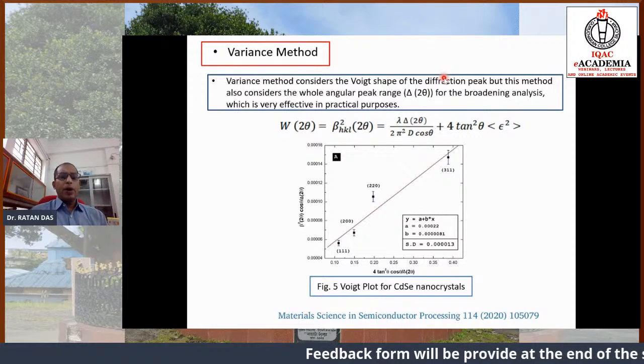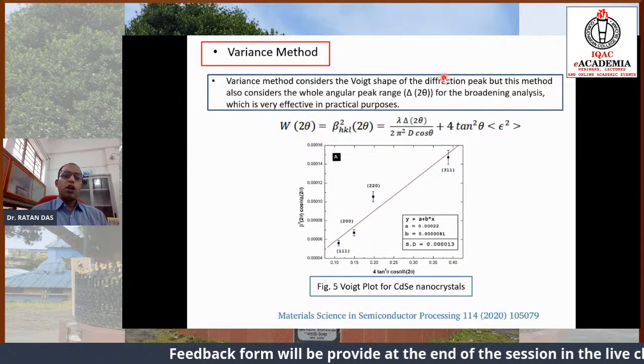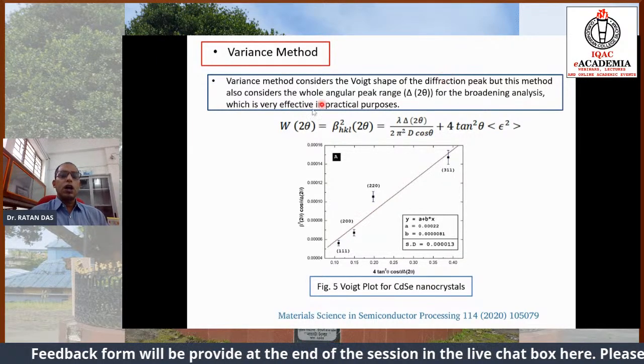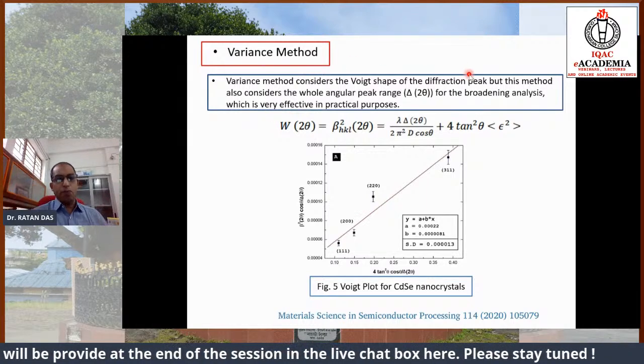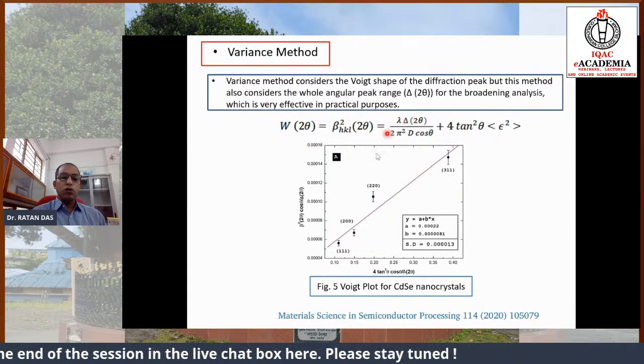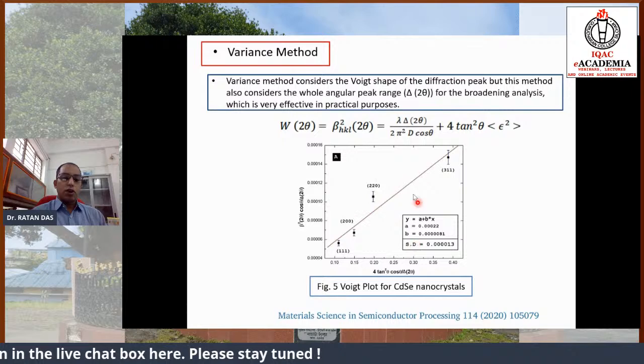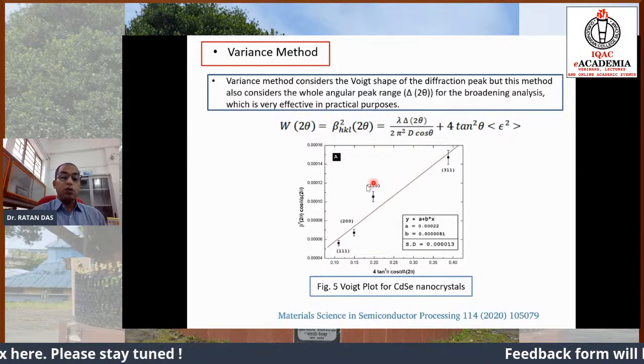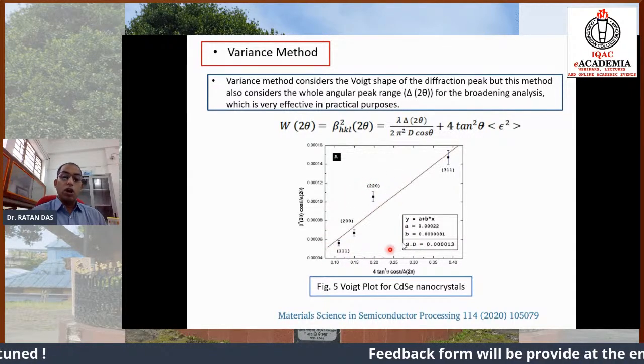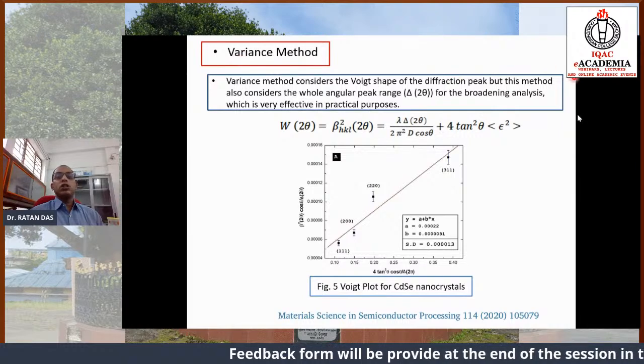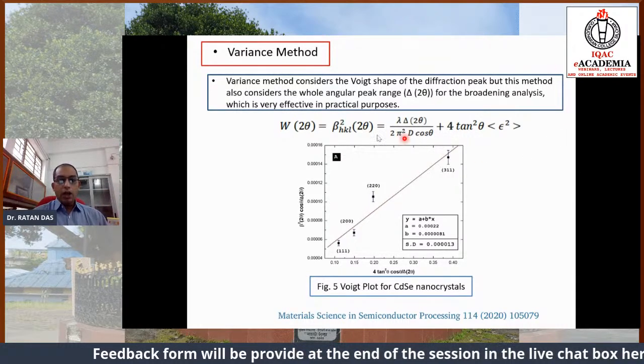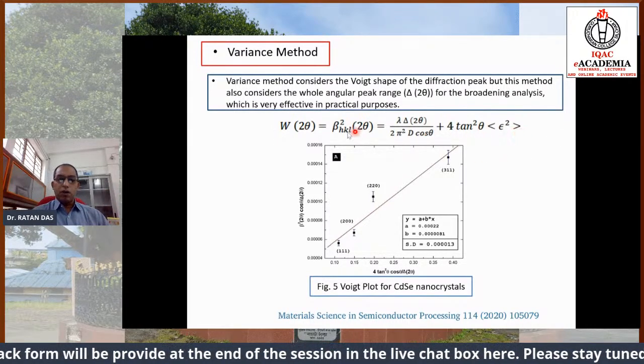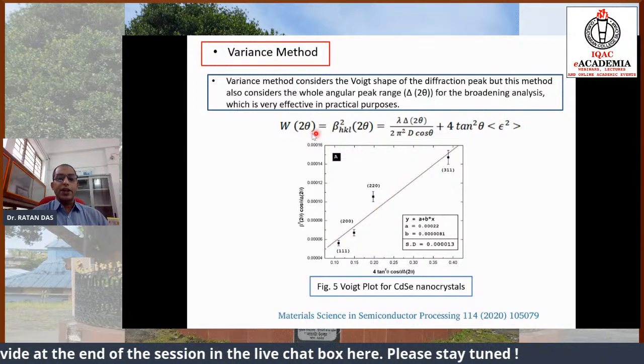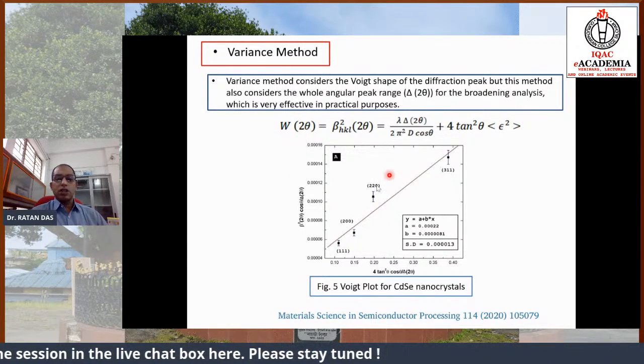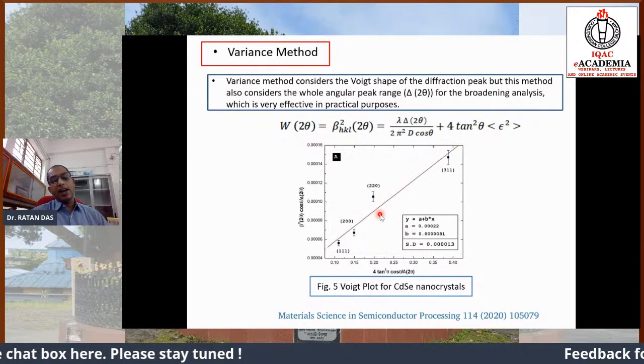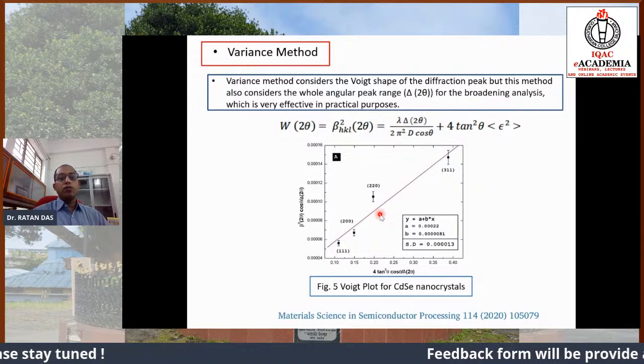Again, there is a variance method, which is a Voigt-shaped method, but it considers the whole diffraction pattern, not only the lower part. The Halder-Wagner method considers well the lower part, but the variance method considers the whole pattern effectively. And there is a complicated formula that has been obtained. Using this formula and plotting the terms, we can obtain the size and strain value from the variance